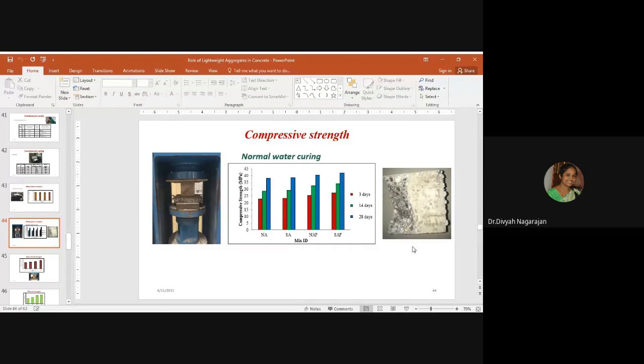The sintered fly ash aggregate concrete was designed to have a similar compressive strength as the normal aggregate concrete. The M30 grade of concrete was achieved, and the target strength was also achieved through the mix design. And this is the split section of the specimen.